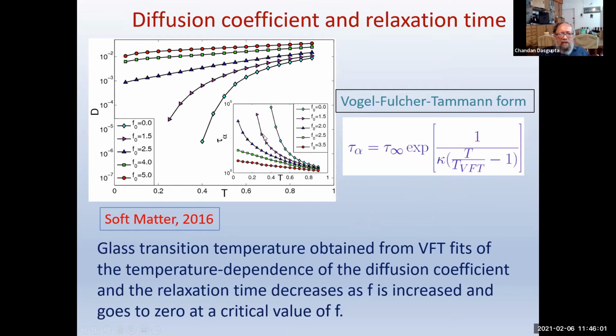It just says that, as you can see from here, as I'm going from here to there, to there, the growth of the relaxation time is quite rapid when there is no activity. But then as you turn on the activity, the dynamics becomes faster, and eventually it becomes very weakly temperature dependent as you go to sufficiently large activity. So here, the liquid is going to freeze. One is going to see a glass transition, but here, the liquid is not going to freeze at any finite temperature, and you don't get a glass transition temperature. Same thing from the diffusion.